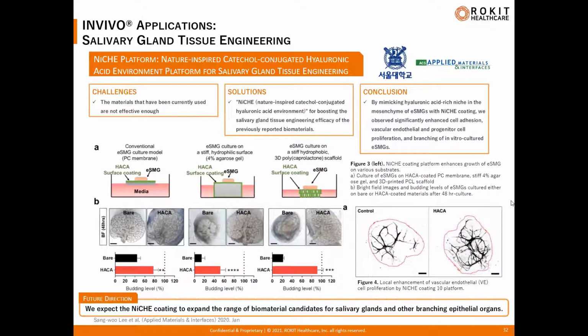Here we've got an example of application in creation of salivary gland or branching epithelial tissues. They call this the nature-inspired catechol-conjugated hyaluronic acid environment, or NiCHE, for boosting the salivary gland tissue engineering efficacy of the previously used biomaterials. Long story short, they combined this hydrogel coating technology with 3D printed porous PCL scaffolds to demonstrate that the highest amount of salivary gland tissue was formed compared to non-coated ones, or the ones using the traditional membranes of soft agar gels or agarose gels. The group believes that this can also be applied for vascular endothelial cell growth, and they look forward to applying this platform to create better human models of other branching epithelial organs.